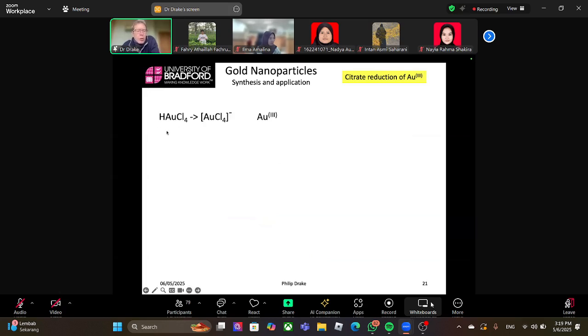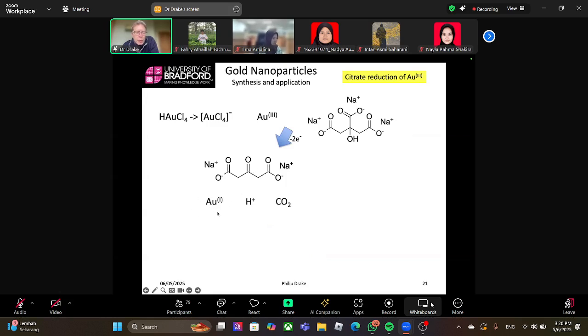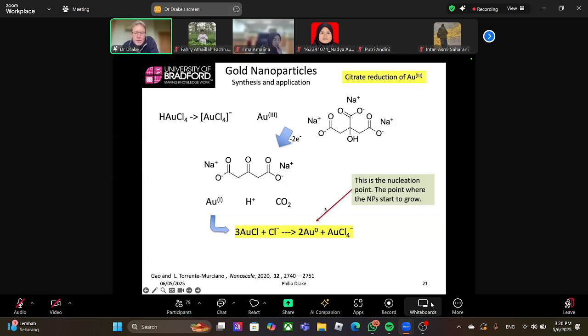So what's happening? Gold aurate dissolved in water. Sodium citrate. They combine, it's a 2-electron reduction. The sodium citrate loses a carboxylate group and water, and it gives you gold 1. So you go from gold 3 to gold 1. It's still ionic gold, and CO2 is produced. 3 of the gold 1 ions come together with chlorine to produce 2 metallic gold atoms, and then 1 gold aurate again. So this is a cluster of just 2 atoms coming together. They're gold 0, which means they're now metallic gold.